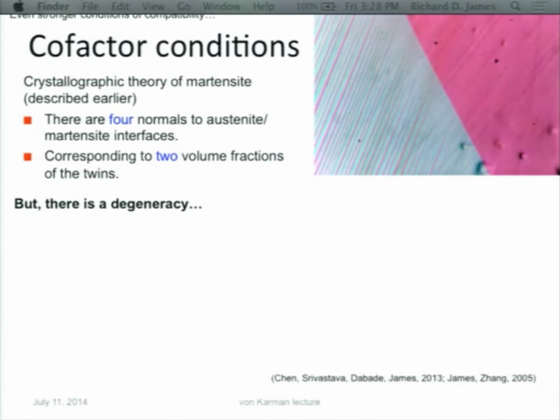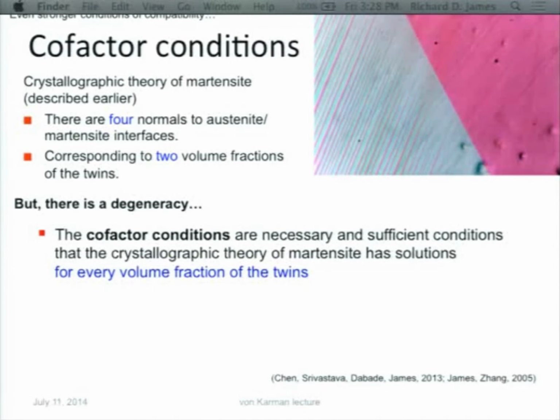And here's what we came up with. Again, we looked at that crystallographic theory of martensite that describes this as a minimizing sequence of some energy. And we realized there's a degeneracy there. So this was the standard situation: 4 normals and 2 volume fractions. We realized that if you satisfy certain stronger conditions, then you could have infinitely many solutions of this problem. You could continuously vary the normal, and you could continuously vary the volume fraction, and you would have low energy interfaces in the same sense as I described earlier.